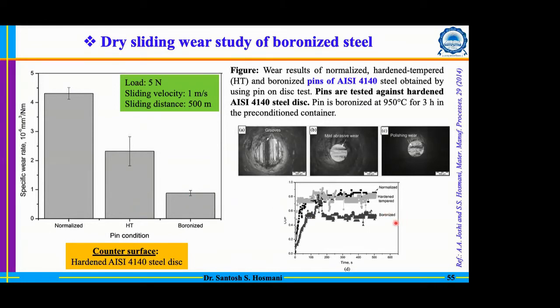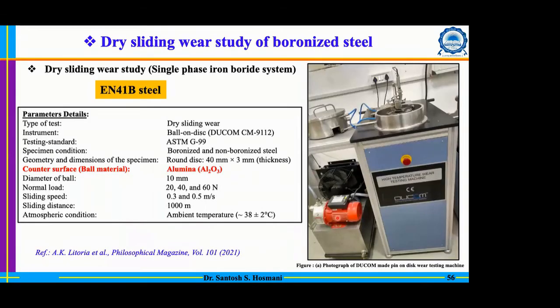And if you see the right-hand side graph, there also you can see the coefficient of friction is very low compared to that of normalized and hardened tempered. However, that cannot really be called extremely low because it is still about 0.5. We are not really happy with this coefficient of friction. 0.5 is a very high value. That means we are getting a very good improvement with respect to loss of material, but the coefficient of friction is not really great. And for that purpose, we need to see the effect of DLC coating. That was our motivation to go with the DLC coating, and it actually helps us.